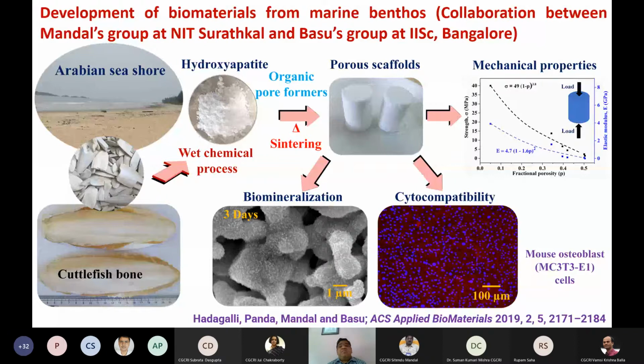One of the important things that we have established is that in the marine derived bioceramics, if you make this scaffold with different porosity, the strength and elastic modulus vary with porosity, and it shows a kind of non-linear relationship. And one of the unique things of the marine-derived bioceramic is that it supports biomineralization, in terms of calcium phosphate crystal nucleation and growth, very rapidly within 3 days of incubation in simulated body fluid.